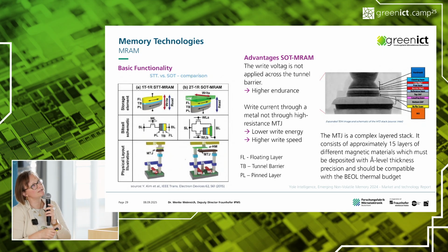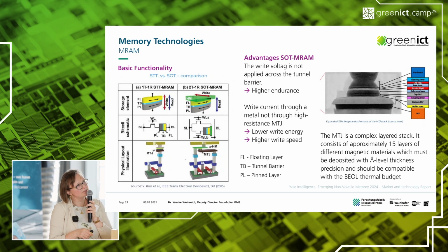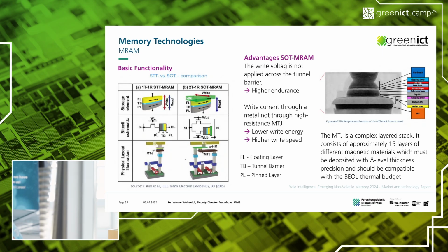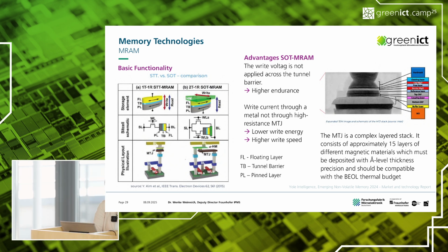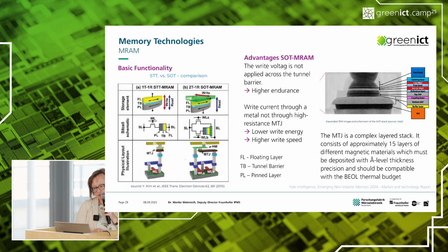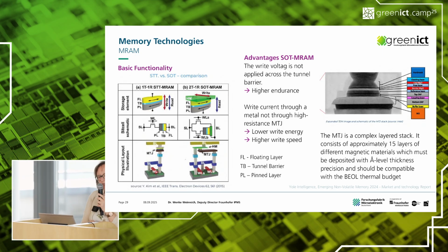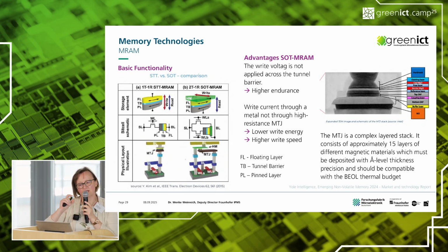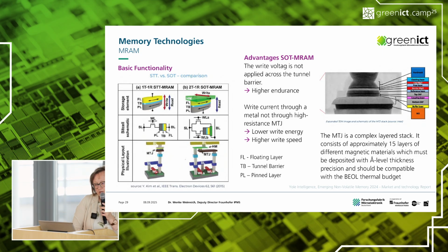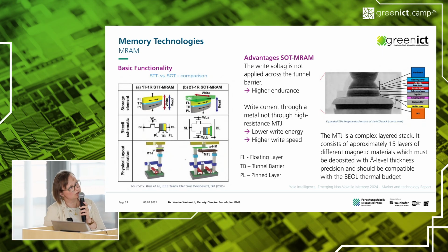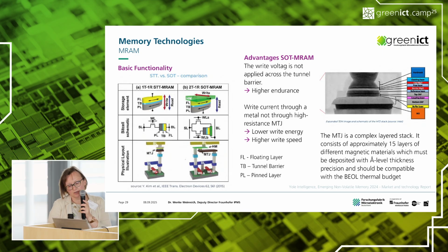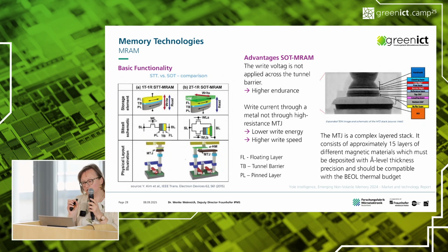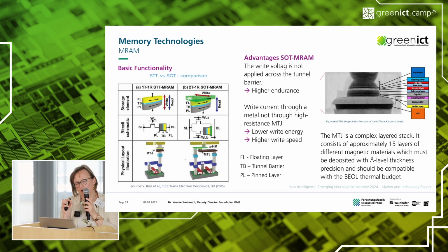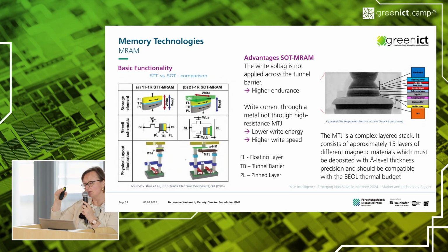At first I want to show you, as I said, okay, here it looks quite simple, but at the end it's really not simple. To build such a kind of memory element, such a kind of memory stack, I show you here these TEM images of a real MTJ. MTJ is magnetic tunnel junction. This is just the name of this kind of material stack. And this is a really, really complex layer. So not only 3 layers: to have a pinned, a floating, and a tunnel barrier, you need up to 15 layers of thin materials, which are sometimes really in the angstrom level. So you really have to put angstrom level controlled layers on top of each other, so that it really works.